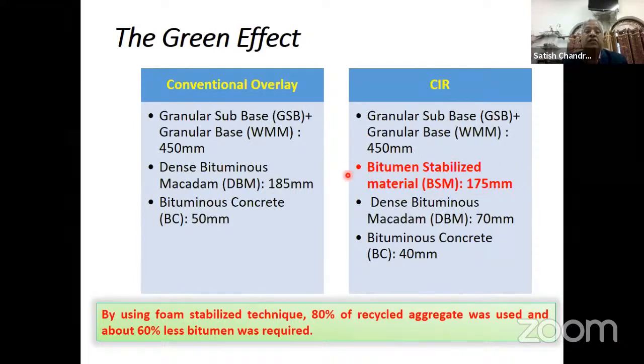Now this is the material which is excavated from the site. Same material is used with some virgin aggregate depending upon the grading required and grading available, with some rejuvenator. You use the same material and compact it there in the layer of 175 millimeter. And above that, you provide a DBM layer of 70 millimeter and then 40 millimeter. So this is what basically done. And by foaming technique, you can use up to 80% of recycled aggregate. That will require 60% less bitumen, because bitumen is already present in the top layer. So that bitumen can only be rejuvenated. You can use that bitumen.